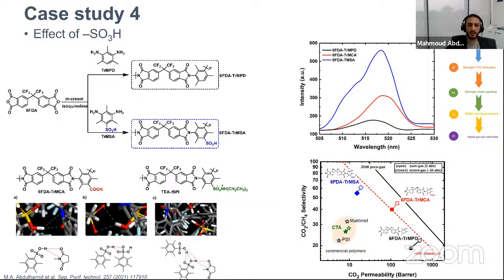selectivity. So when we look at the performance of mixed gas in this case, we can see these are the places of the commercially available materials. This one is the performance of the non-functionalized, which has high permeability and low selectivity. This one has even higher selectivity, but still keeps good permeability. And this one has the extreme, the highest selectivity compared to the others, the one that contains SO3H.